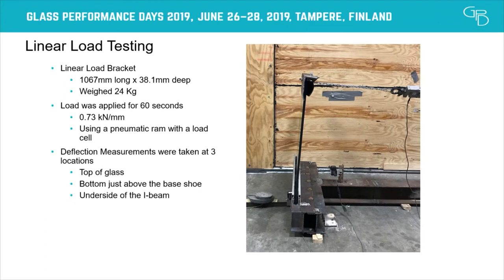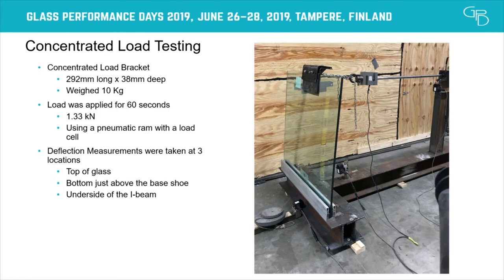And then we took deflection measurements at 3 locations: at the top of the glass, right above the base shoe on the glass, and then underneath on the I-beam, right here. So the same for the concentrated load. We had a smaller bracket made that went in the center, and it was 292 millimeters long, and again, only about 38 millimeters down from the top of the glass. The load again was applied for 60 seconds, and we again had all of the deflection measurements at the same spot.